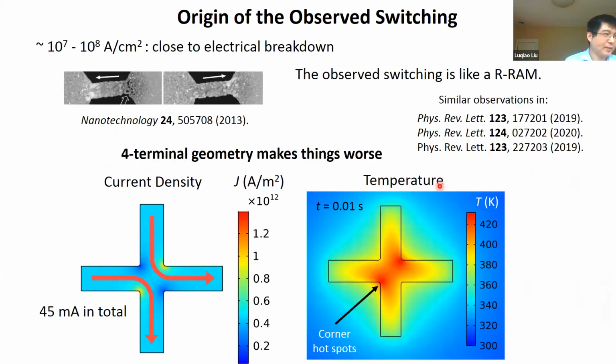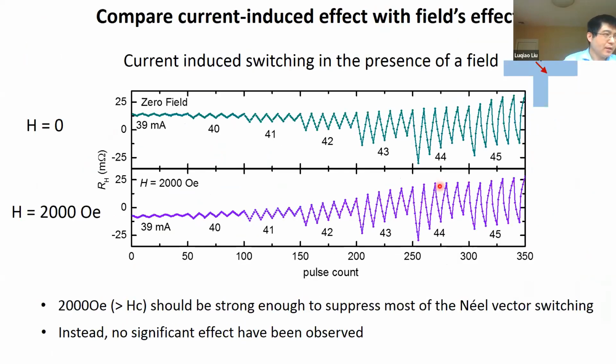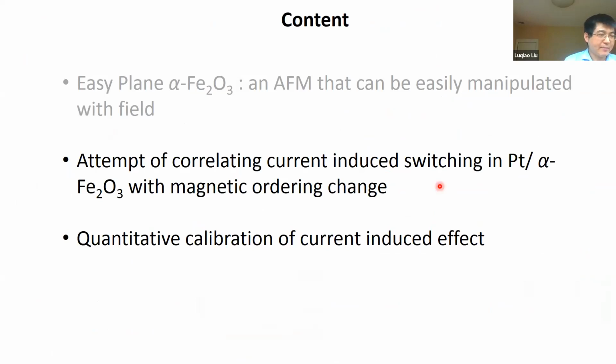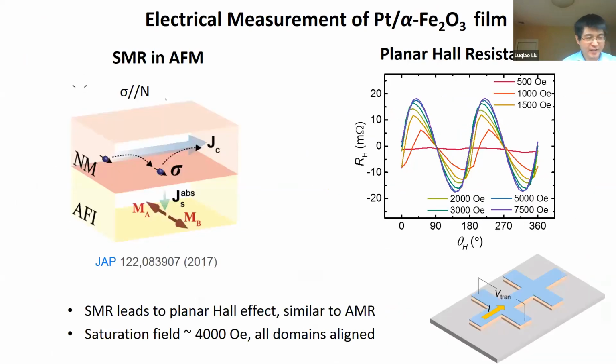So basically, the mechanism for SMR is that when you have an injected spin parallel with the moment or parallel with the Néel vector direction, you get absorption. Yes. So for antiferromagnet, for ferromagnet is when sigma is parallel with m, then you get the largest absorption. So remember the Néel vector is orthogonal to the net moment.